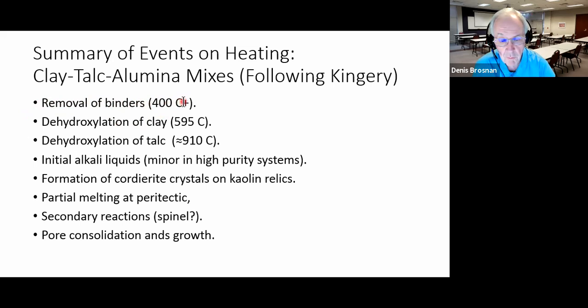And what happens is you've got to remove those binders, and that requires probably 400 degrees C and higher to get rid of them. Remember, we want to get them out before we form any kind of liquids. We're going to dehydroxylate the clay in the area of 500 to 600 degrees C. We're going to dehydroxylate the talc. It has a fairly broad endotherm for dehydroxylation, but up around 900 to 910 degrees Celsius we can form some initial and perhaps transient liquids. And that always happens above about 1,000 degrees C.